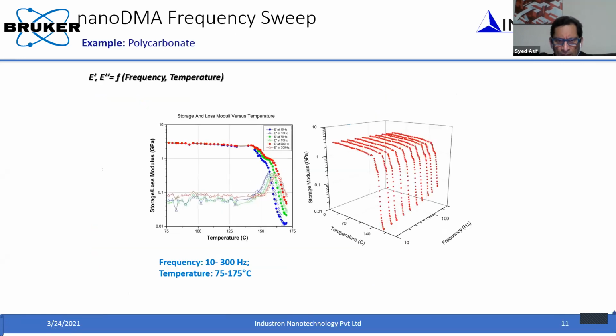Now, if you have the capability of changing the temperature, then you can do that at different temperatures. Here, I'm showing it for a polycarbonate material, where these experiments were done at different frequencies and at different temperatures. By looking at this data, we can collectively construct a master curve, which is very useful for the polymer chemist. Then you can understand how the properties are changing. For example, here the storage modulus as a function of frequency as well as temperature. At some temperature, you can see the glass transition, and you can also observe that from the tan delta curve at the bottom. So you can pretty much completely characterize the viscoelastic behavior of the material by doing these experiments.